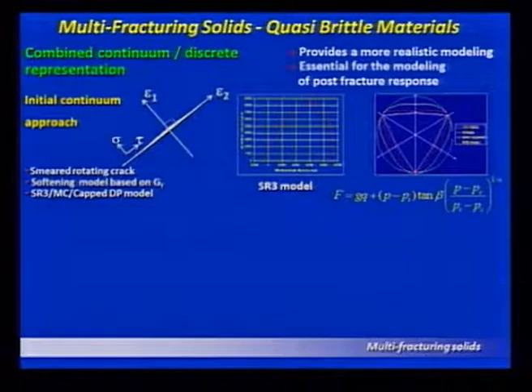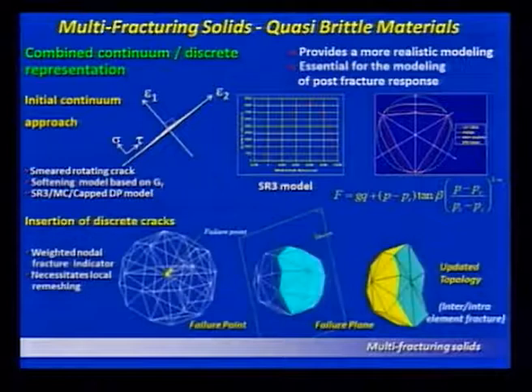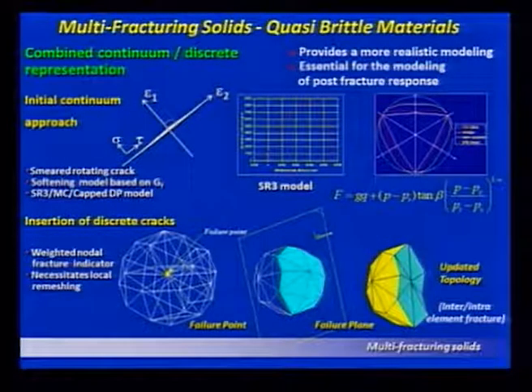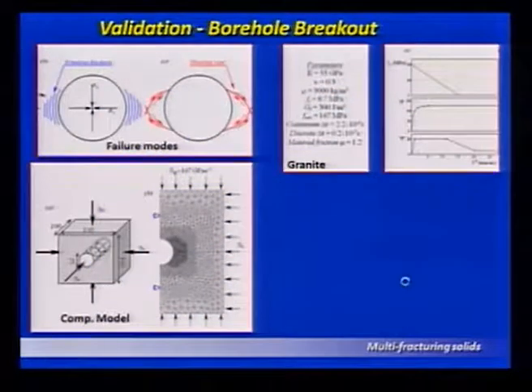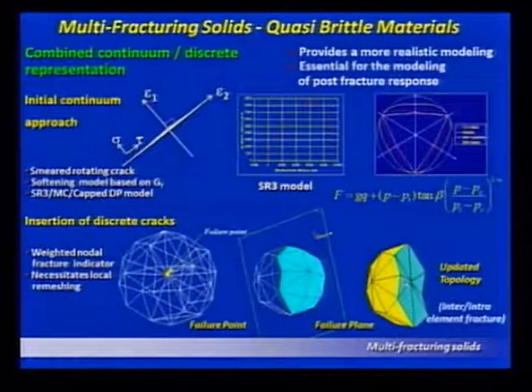And then as soon as you detect fracture on a continuum basis, we actually insert a fracture on a nodal point basis. So we go to every nodal point where the region surrounding it is fractured. We put in the fracture surface whose direction is given by the conditions of the surrounding elements, and that means you introduce another node here. Therefore, we end up having to locally remesh the material to accommodate the fracture.